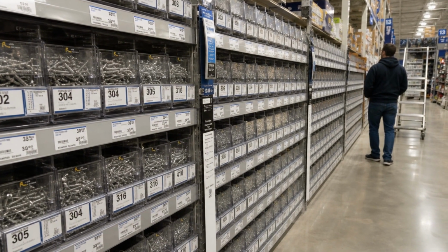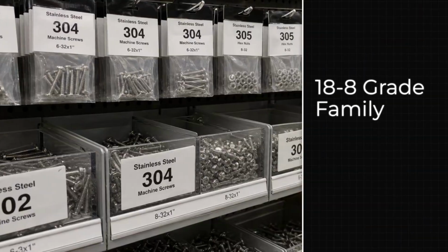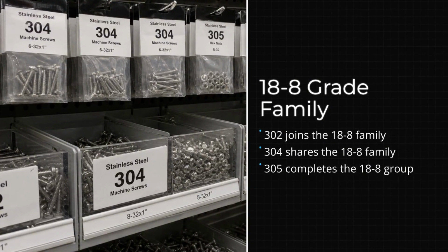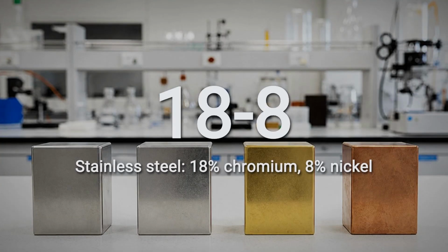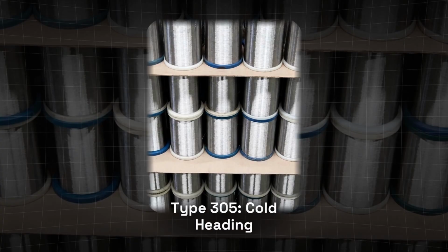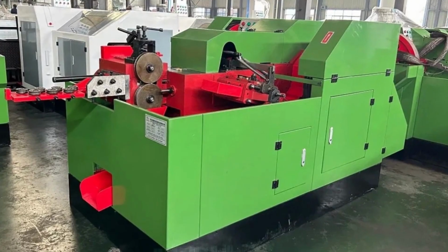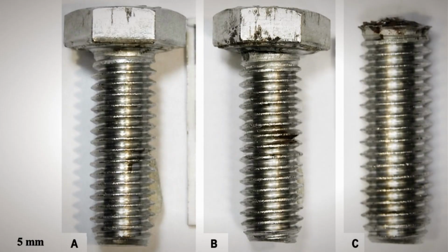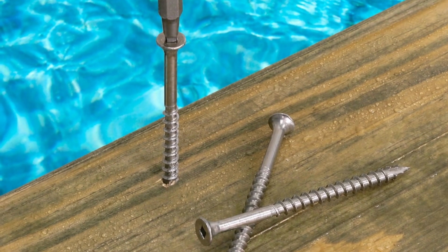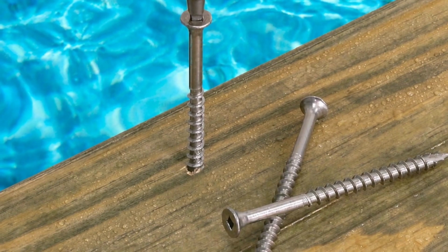4 grade numbers matter once you are standing in that aisle. Types 302, 304, and 305 make up what the trade calls 18 to 8, named for roughly 18% chromium and 8% nickel. Their corrosion properties are close enough to treat as equivalent. Type 305 exists for a specific manufacturing reason. It was developed to improve the cold heading qualities of 18 to 8, meaning it forms into screw heads without cracking or galling during production, which is exactly why deck screws end up made from it.